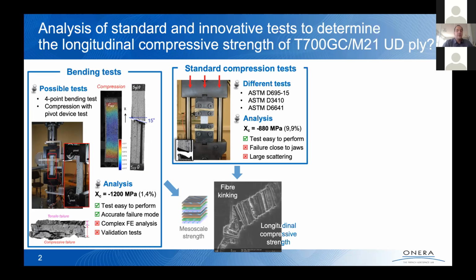But if you observe precisely the failure patterns that you can see on this slide, you can see that through the thickness, you can observe 2 different failure mechanisms. One is due to the fiber failure in compression, and one is due to the fiber failure in tension. And you can see that it is really challenging to predict the competition between these 2 failure mechanisms. Therefore, such a bending test, in my opinion, should be considered as a validation test for advanced damage and failure approaches instead of an identification test.